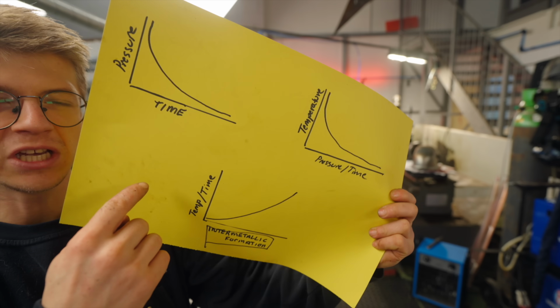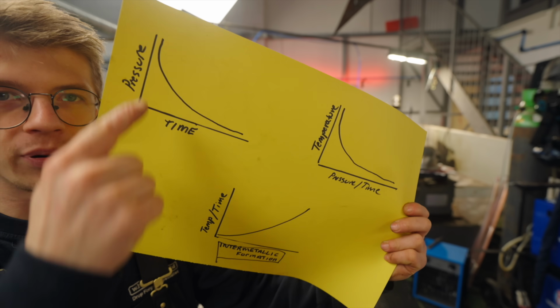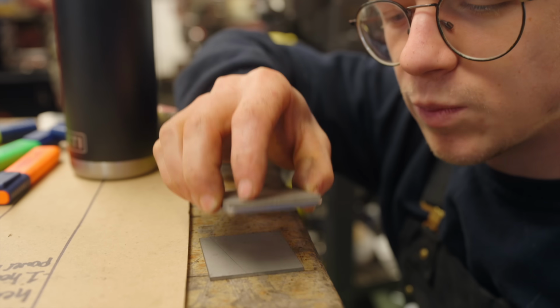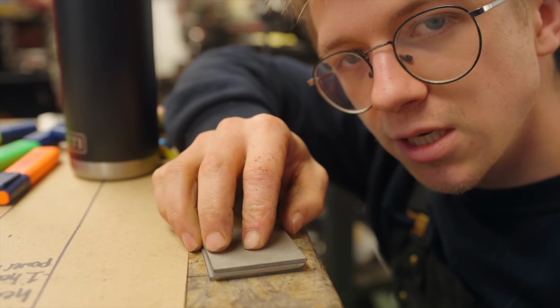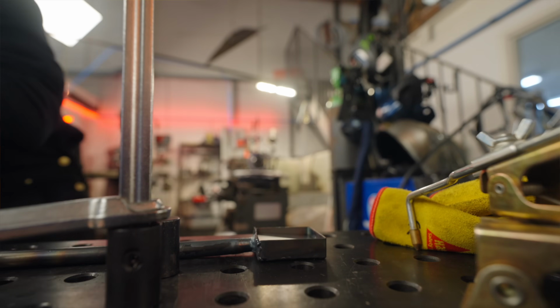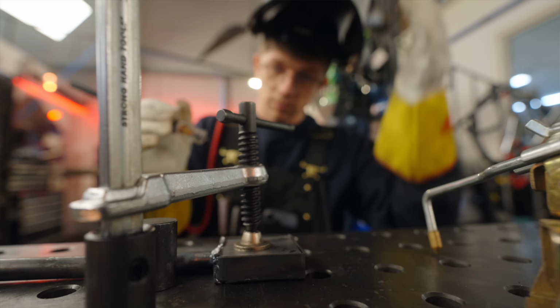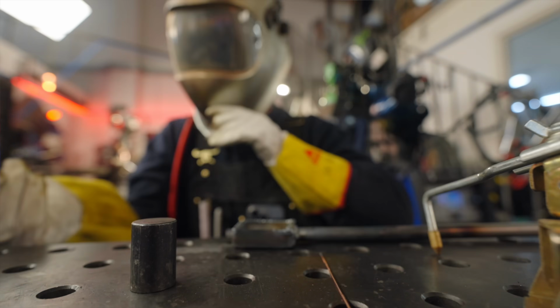So with this, we're left with the only thing we can maximize being the pressure, and that time at temperature needs to be reduced as much as possible. And so the idea he presented was bond the titanium straight to the steel as quickly as possible, with as much pressure as possible, and then immediately quench it. Heated, bonded, hardened in one shot. And that's why we're going to be trying it right now to see how it compares to our other freshly heat-treated samples. Here's the plan.